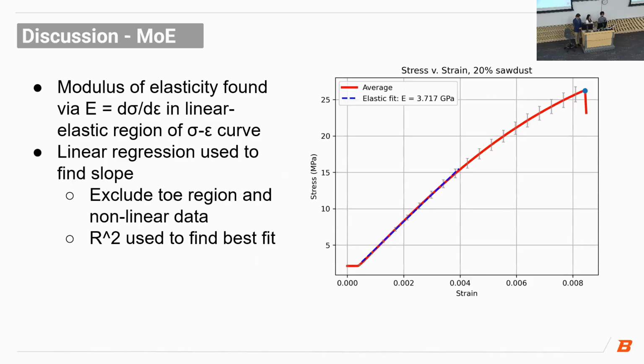And how they were fitted, again, was through a least squares model or a linear regression model. I would just take one point and then take another point, draw a straight line between them, and then fit it as best as possible to that region, and then determine the slope from that straight line. And then we would measure how well that fit through an R-squared score. The closer it was to 1, the better. And here's an example of it, of us including or excluding the toe region and excluding anything that was nonlinear.